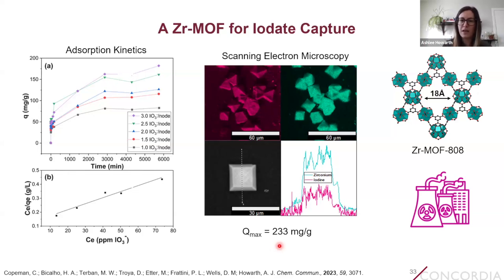And so we can use scanning electron microscopy coupled with energy dispersive X-ray spectroscopy to start to understand how the iodate is incorporated in the metal organic framework. And so what we can see here is that both the zirconium and the iodine are evenly distributed throughout the crystallites, which is usually a good sign that adsorption is not only taking place on the external surface, but actually in all the internal surfaces of the MOF as well.